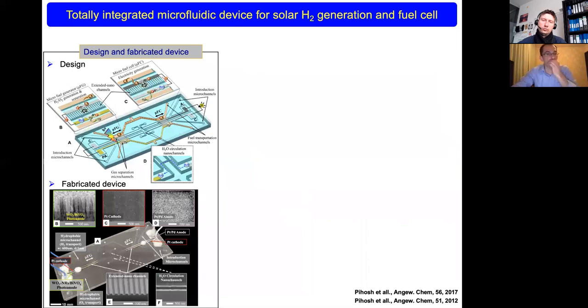So this is the actual design, and this is the fabricated device. This device was realized on quartz plates. What we can see here is the integrated photoanode material, and the SEM image is shown here. It was recorded by SEM directly from this device. And the integrated platinum cathode and the platinum anode. And this is an SEM image of the extended nanochannel, I mean the arrays of the extended nanochannels, which are located here and here. And this nanochannel, used for the connection of these two devices, is located here.